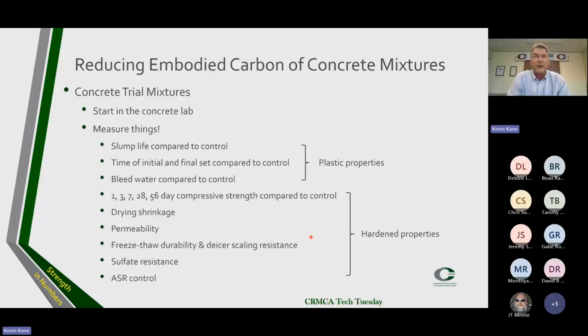But time of initial and final set. The worst thing you could have when you don't have a concrete mix that supplies a good amount of bleed water to the surface is a concrete mix that's very retarded and takes a long set. That's not a good combination. Long set time and little bleed water is not a good combination because what do we get then? We get plastic shrinkage potential.